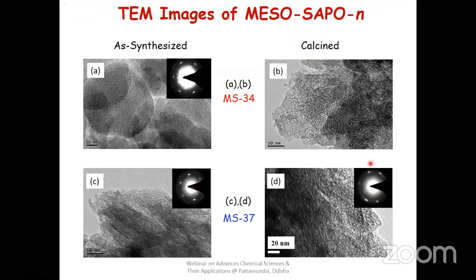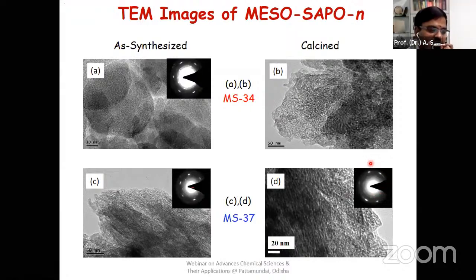You know that if the materials are amorphous in character, you will not get a spot pattern in the ED pattern, that is, the electron diffraction pattern, which tells where the atoms are present and how they are arranged. So the presence of a spot pattern indicates that the atoms are arranged in a uniform fashion, and this material has very good crystallinity. That is what indicates the structural aspect.